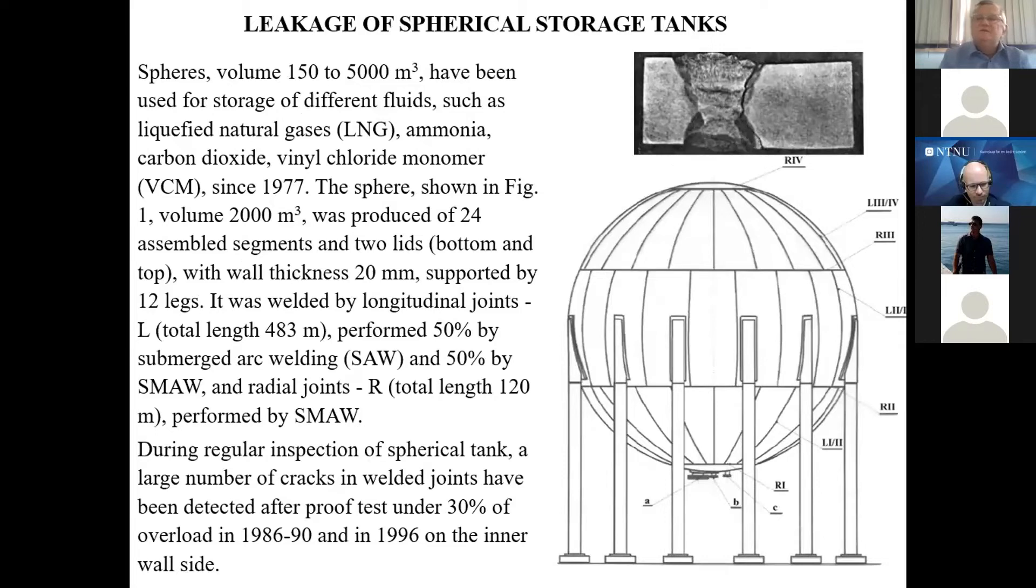So that was the second topic. We move to the third one. It is also back in the 80s a very important and difficult practical problem about leakage of spherical storage tanks. It was the first generation of high strength steels. A bit of microalloy with some vanadium. But most important is that production technology was not as good as today and that carbon content was a bit higher than today. So that steel was susceptible to cracking,